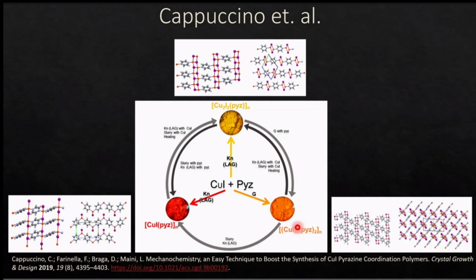They also looked at thermogravimetric analysis, which allowed them to confirm these results. Under thermogravimetric analysis, you basically heat the product until it decomposes, and you can see what the decomposition products are. They showed that the orange and the red both decompose first to the yellow polymorph and then to copper iodide and pyrazine separated. So all of this supported these thermodynamic relationships.